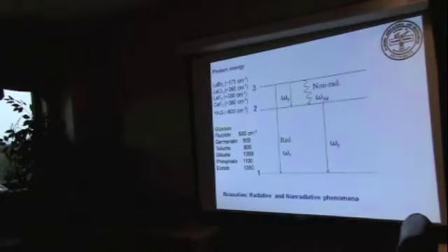So if this energy gap is small, depending on the material in which this ion is, it may just relax here by emitting phonons, or basically it heats up the material. Whenever it is radiating, you say it is a photon, that's a quantum of light. Similarly here, it's a phonon, which is a quantum of lattice vibration. See, when you have any piece of material, inside you have atoms, they vibrate at certain frequencies. Those natural frequencies are the phonons. Those phonon modes are fixed for each material. That depends on the individual masses of those atoms as well as something called the force constant.